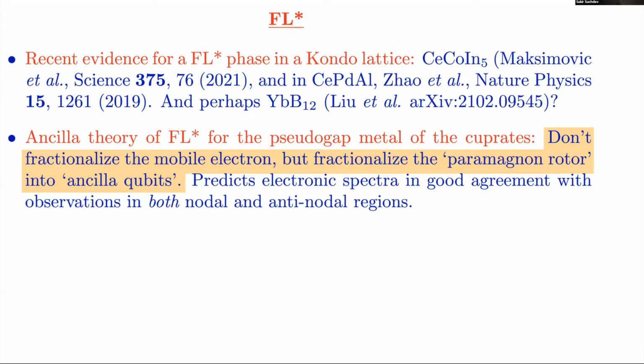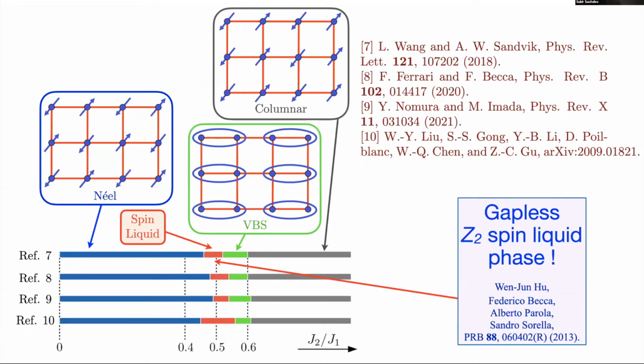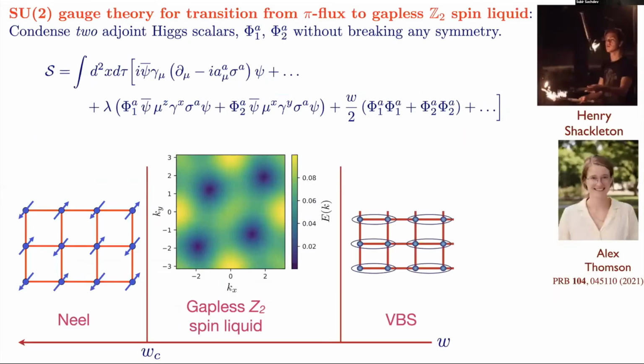All right. So one way to figure out what's a good spin liquid, and I can't resist mentioning this, is to look at the J1, J2 model, just the insulator, because you can just look at the bottom layer, which is insulating. And there's some recent evidence in numerics for a very interesting gapless Z2 spin liquid phase of the type Senthil and Fisher first discussed. And so we've done a lot of work on this kind of phase and also applied it to this particular model in this paper with Henry and Alex.